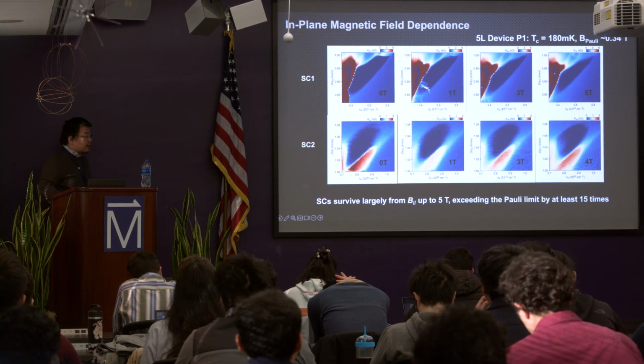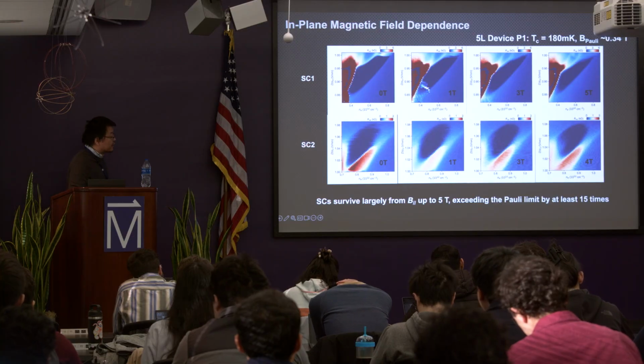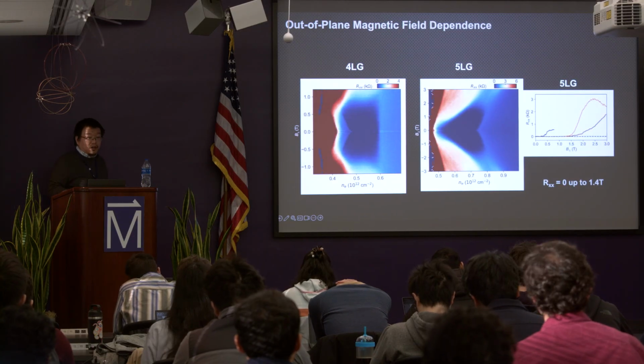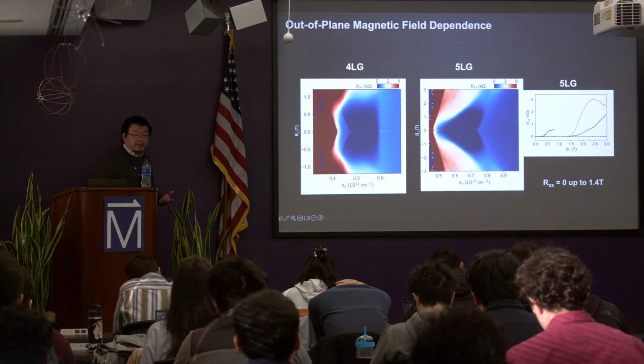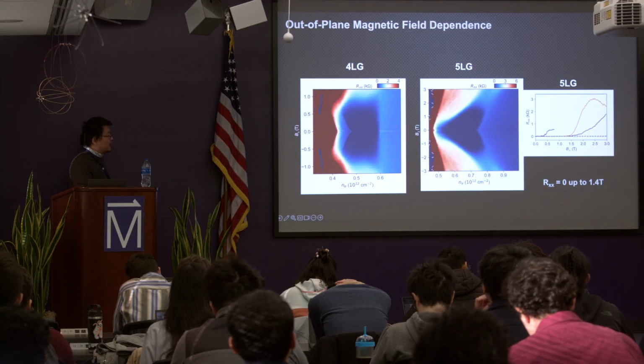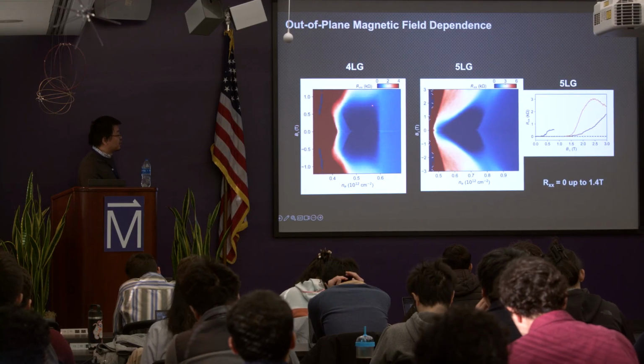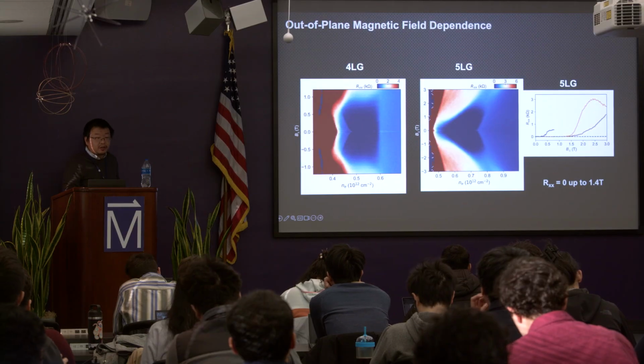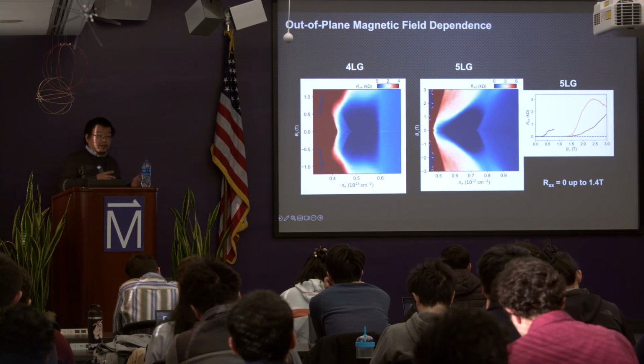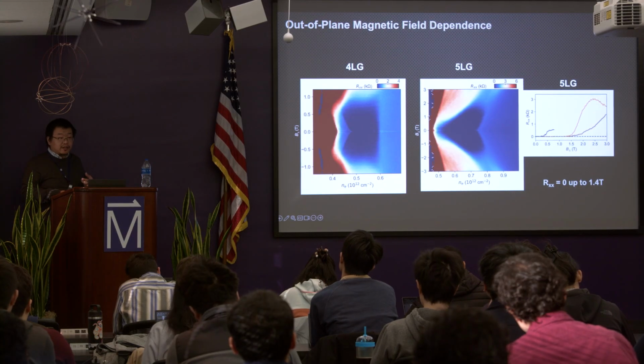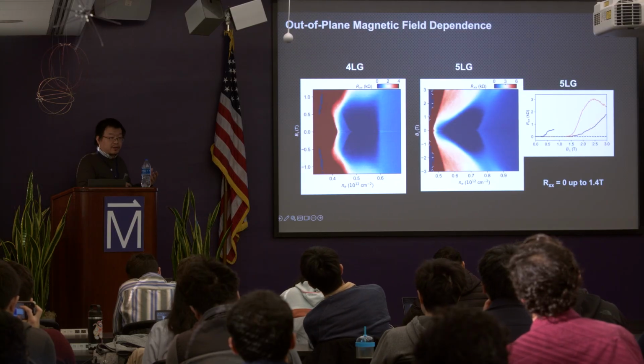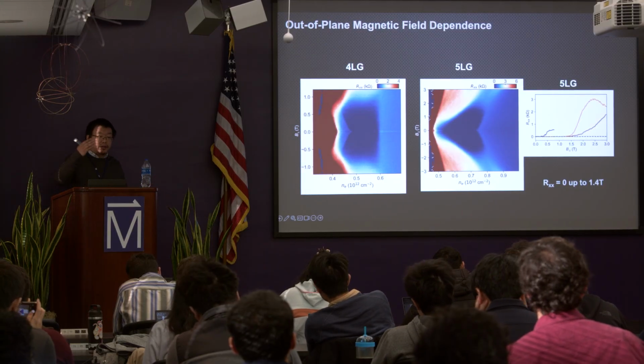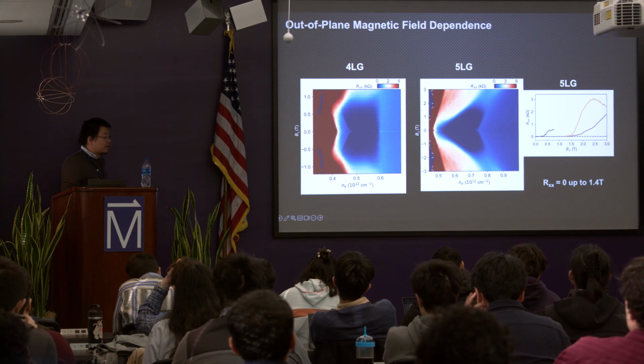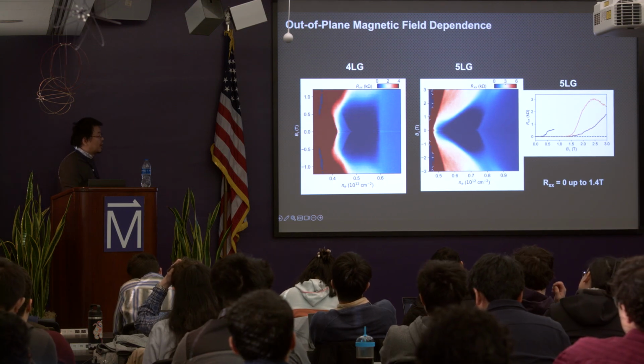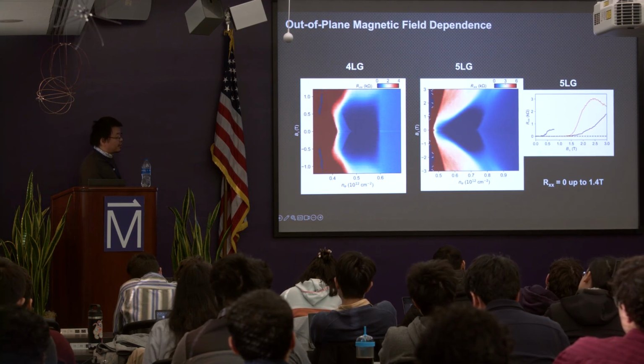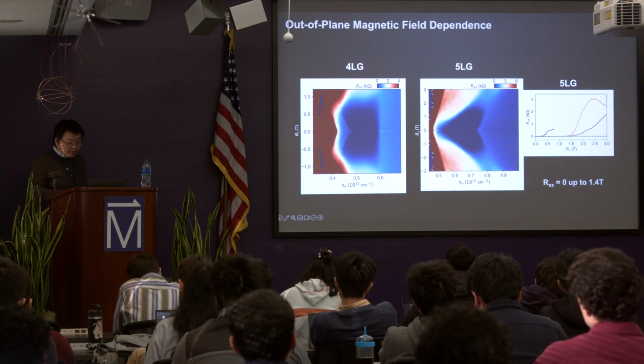More surprisingly, other than the in-plane magnetic field, it actually survives a very high out-of-plane magnetic field. This is very puzzling. For the 4-layer rhombohedral graphene, it can survive up to about 0.6 Tesla out-of-plane field. Remember, similar TC superconductivity, like in tri-layer or 5-layer on the hole side, can only survive up to 10 millitesla. So this survives to almost 1 Tesla. And for 5-layer, it survives to even higher than 1 Tesla. So this is something very bizarre.